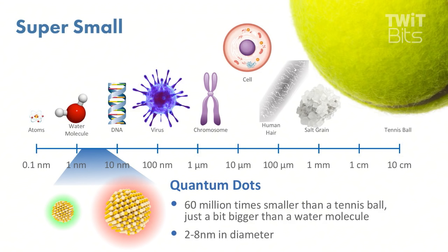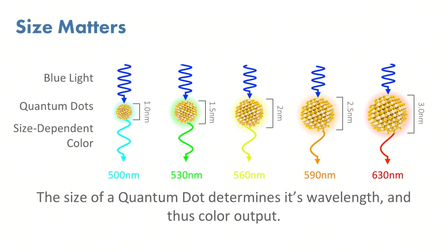Graphic number two shows what we've been doing for the last decade or so — figuring out the best way to make quantum dots that are very uniform in size. Moving from left to right, you see quantum dots varying in size from one nanometer up to three nanometers. It's really important that if you're making one-nanometer particles to emit blue light at 500 nanometers, they're all exactly one nanometer — no 1.5-nanometer particles mixed in. That technology is now very well developed, so you can make very discrete blue, blue-green, green, or yellow particles. We use mixtures of different colors in the QDEF film to create the color primaries needed for really high-definition color.